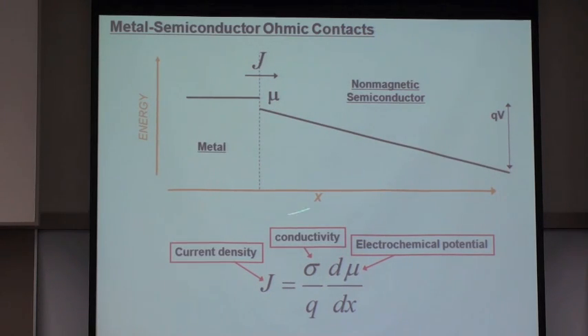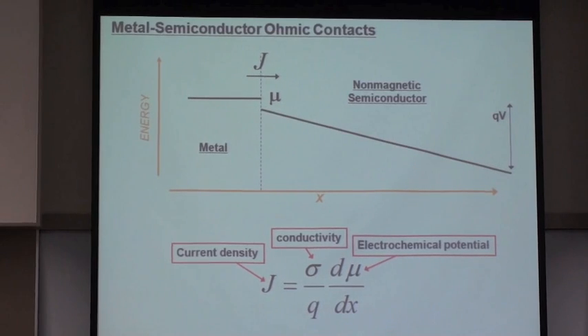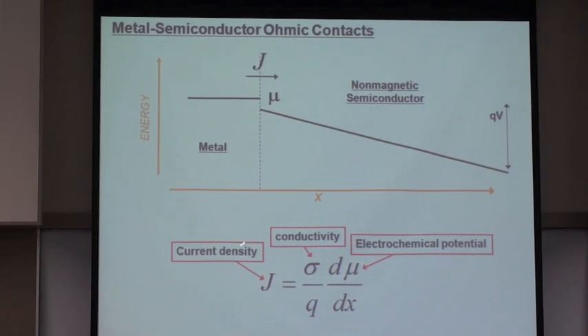So here what I have is a kind of band diagram in which I'm plotting the potential energy on the vertical axis and distance along the horizontal axis. And here what I have is a very simple junction between a metal, which has a high conductivity, and a non-magnetic semiconductor, which has a low conductivity. And so, of course, the current across the interface has to be maintained. The current density J on the left side has to be equal to the current density on the right-hand side.